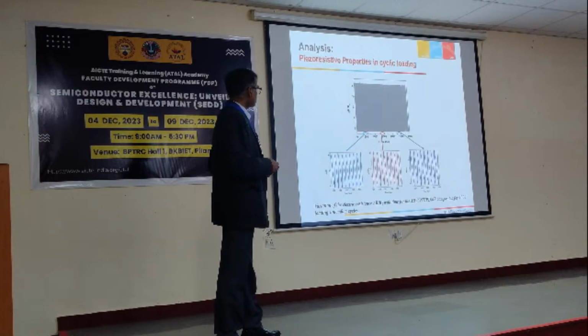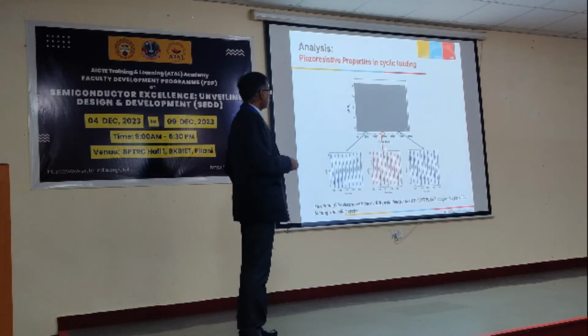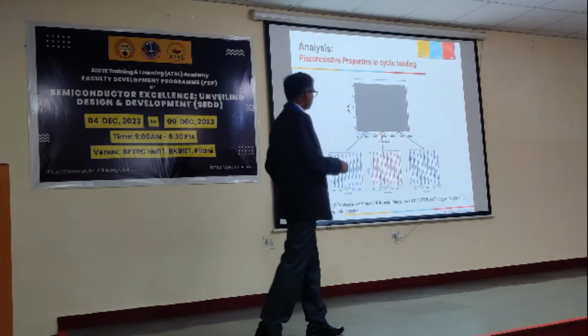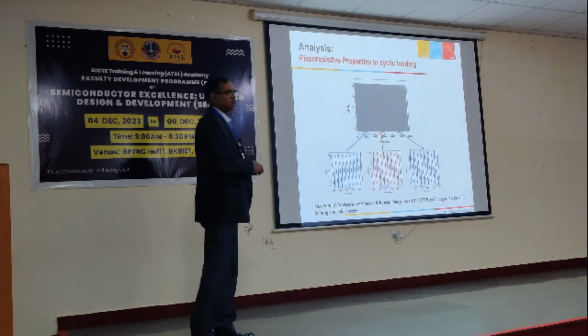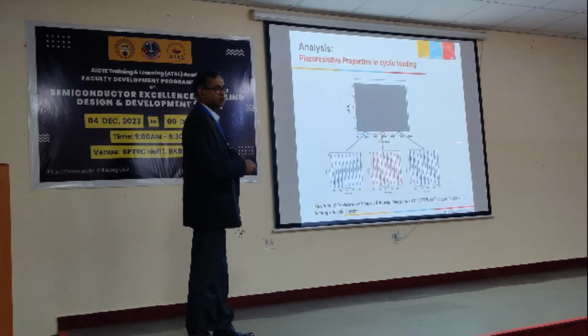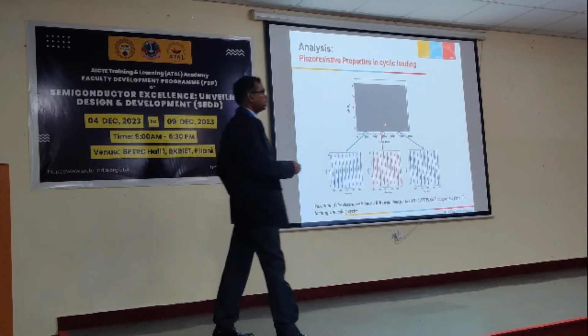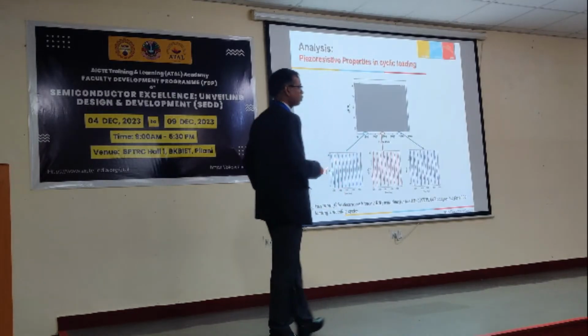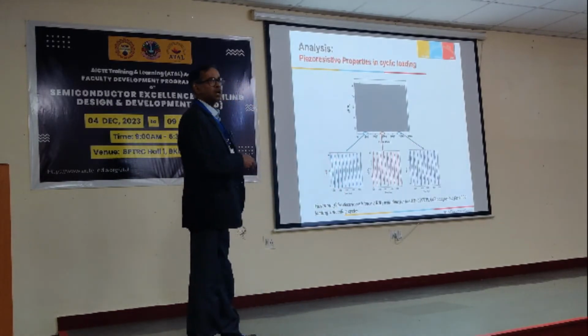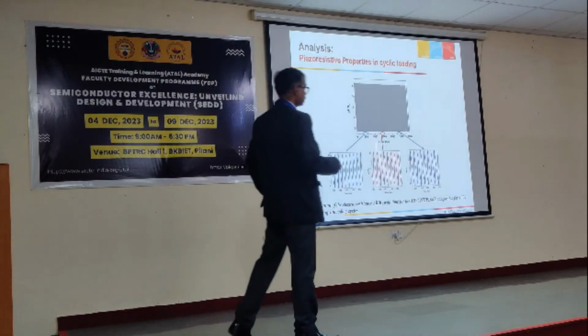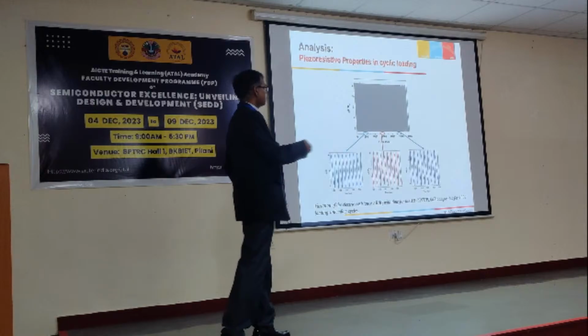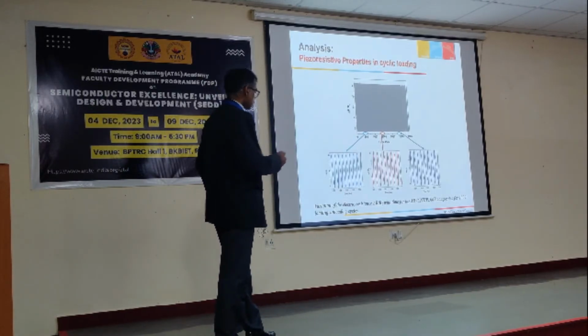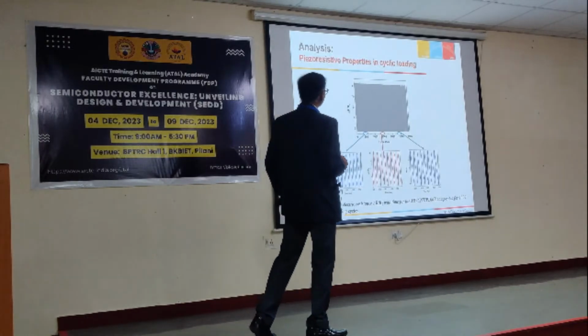But if you actually take out this part and zoom it, it is going to appear like this. Similarly, at a later time, if you take this one, again it is going to show in this way. And at this range, you are going to see. So what is the observation that we are getting here? That when you load, unload, the response remains the same. It is not that with this kind of cyclic loading and unloading, the response of the sensor is going down. So the response will remain consistent, which is the main requirement for the device that you fabricate, that it should actually work for a longer time. So this was also done.